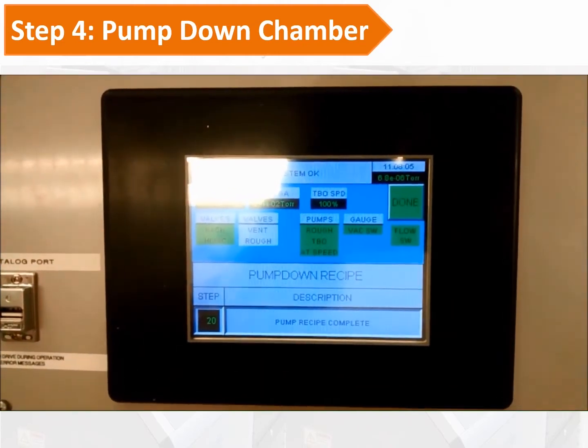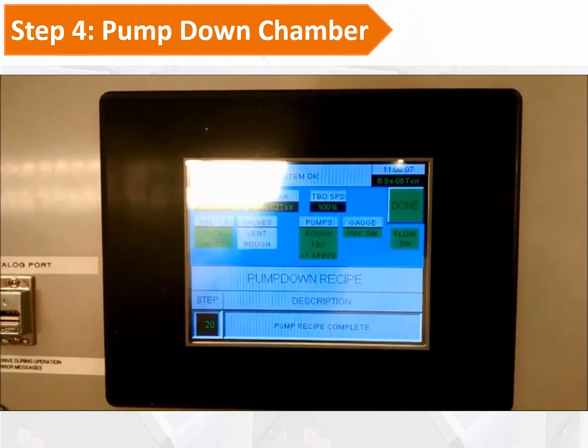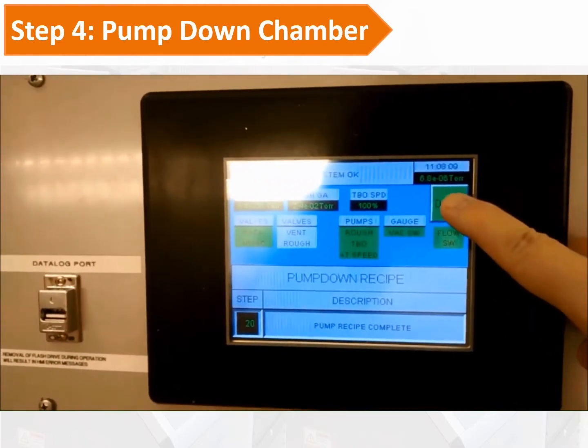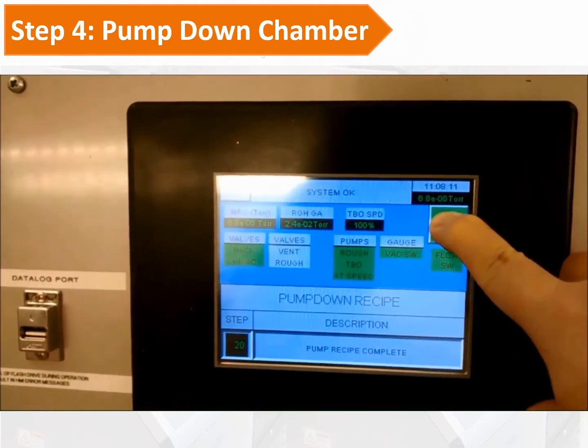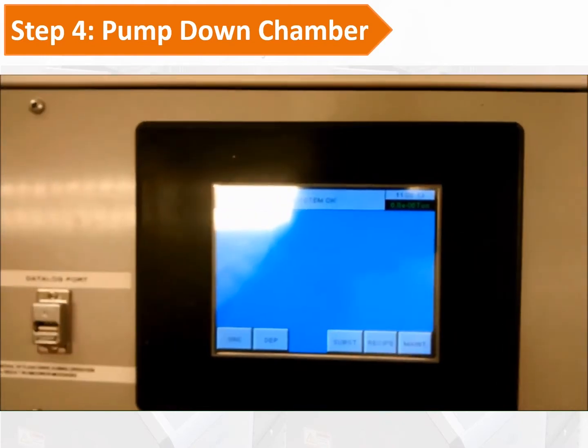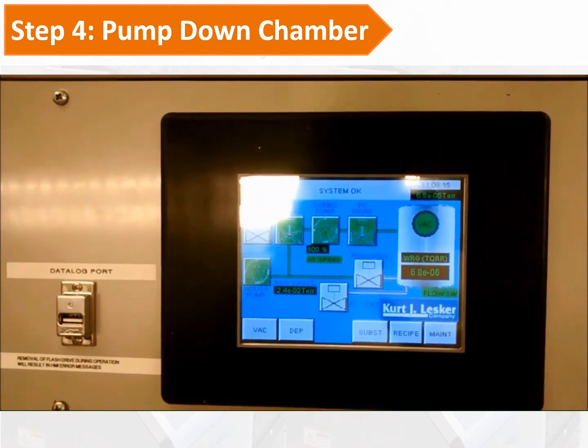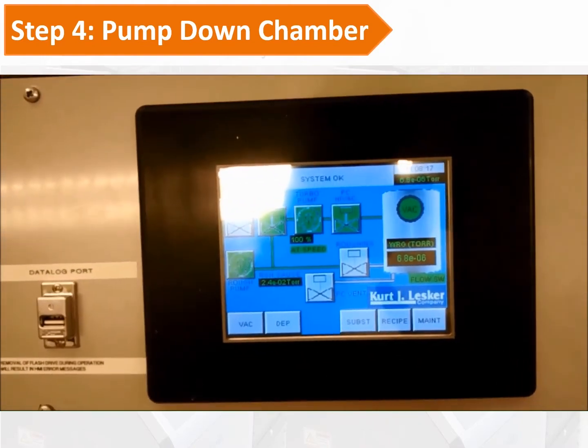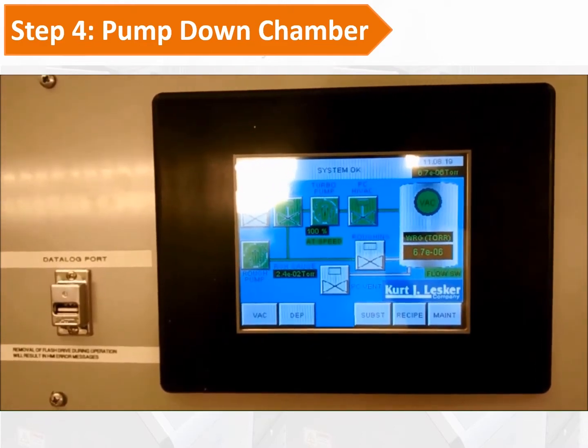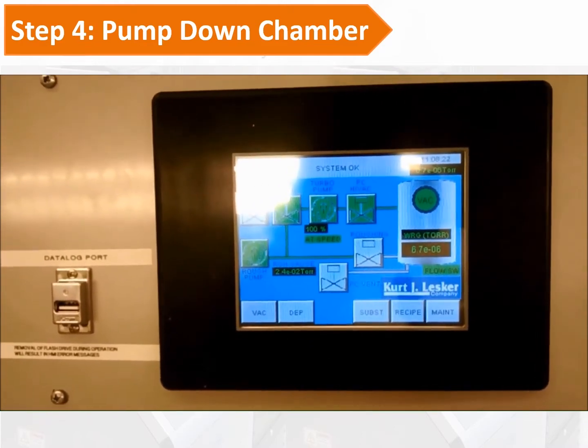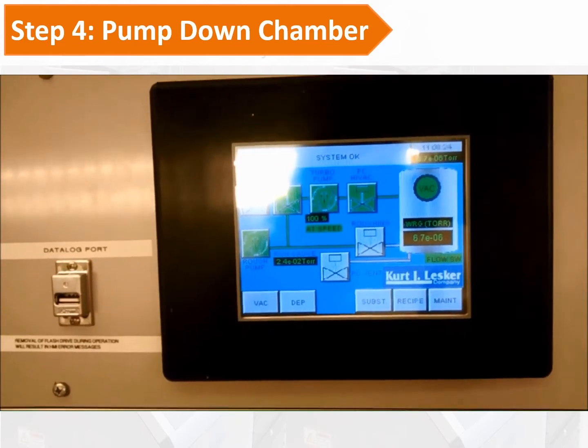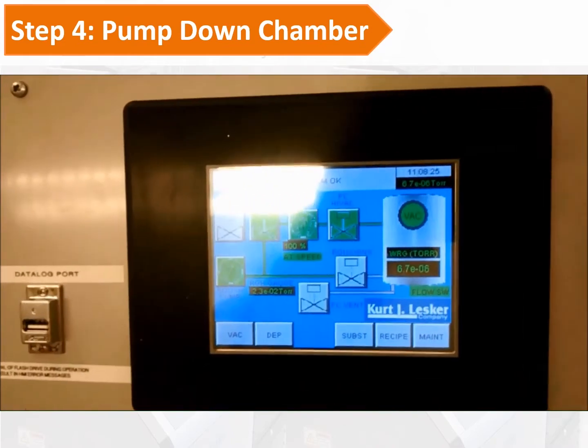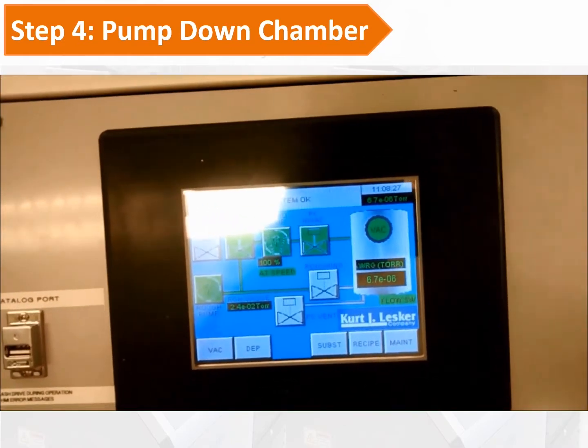And now we can press the done button. It will return back to the vacuum monitor screen. And you can see now the pressure is around 6.8, 6.7 times 10 to the minus 6 torr. We still need to wait a little longer until the pressure is below 5 times 10 to the minus 6 torr, and then we can start the next step.